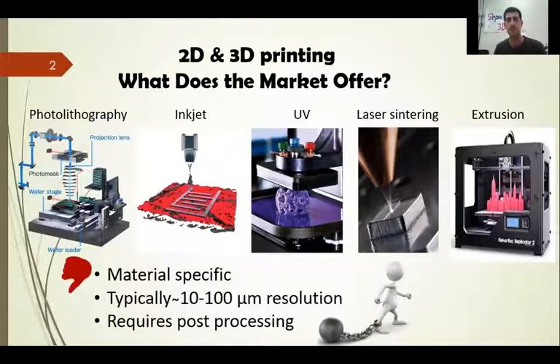But there are some disadvantages with those techniques. The first problem is that some of those techniques are very limited in the materials that they could print. For example, the UV technique requires a polymer that's sensitive to UV light. The second problem is the minimal feature size that this technique could print, between 10 to 100 microns. So if we want to make structures smaller than 10 microns, this technique could not be our option. The last problem is that some of those techniques require post-processing, such as annealing or removing the material supporting the print during the 3D printing process.